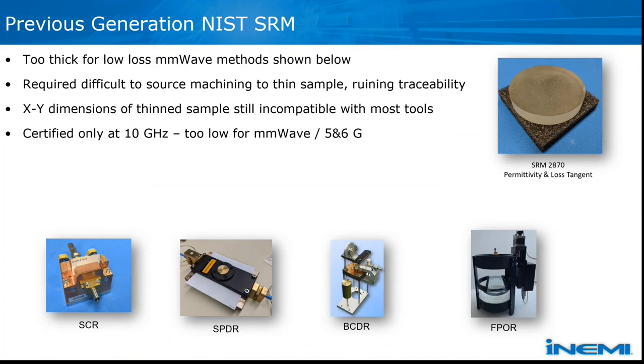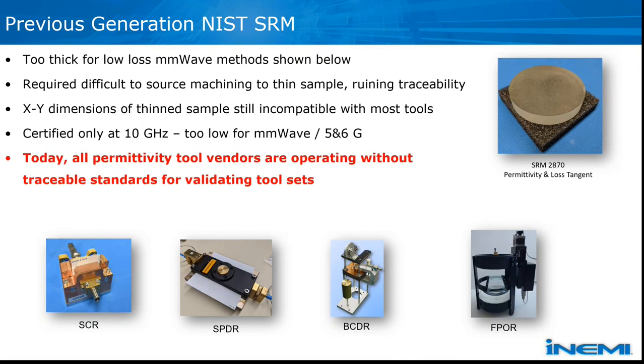Additionally, they're really only certified up to 10 gigahertz, which is way too low for the frequencies of interest for this group, being at millimeter wave and in that 20 to 80 gigahertz range. So today, all permittivity tool vendors are currently running without any kind of traceable standard for validating their tool sets. They're using these sort of interim standards, typically COP and Teflon, as well as some machined Rexolite, this former standard, and fused silica.